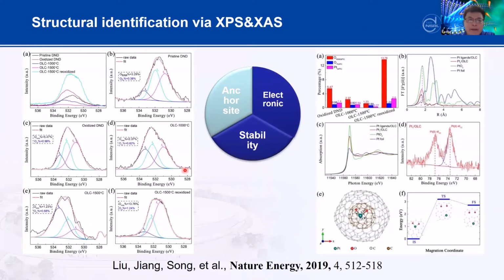So here, as you can see, we try to use XPS first to understand how the atom combines or interacts with the carbon support. Here we found if you control the oxygen functional group in the carbon anchor, you really can control the platinum atom content, which is mounted on the carbon anchor. So that means this oxygen group is really a key parameter for this kind of mounting. Then we also use XAS to study the structure, because this is so tiny an atom. So we study the Pt XAS, and as you can see, this is the R region and this is XAS.